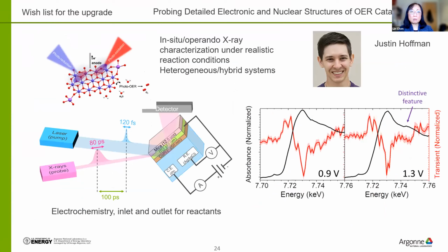So Emily did that. Now, this continues into the wish list for the upgrade. Justin Hoffman, now a postdoc at Argonne, will continue Emily's work looking at the Co-Pi, but under in situ operando conditions. Justin designed the cell in collaboration with Xiaoyi's team, looking at this photoactivity. At that time they used 400 nanometer excitation, which is supposed to reduce the cobalt. That's what is seen here. That's a preliminary result, but it indicates that this combination of electrochemistry and photochemistry could fit the need of many catalysts that can have photoactivity in future studies.